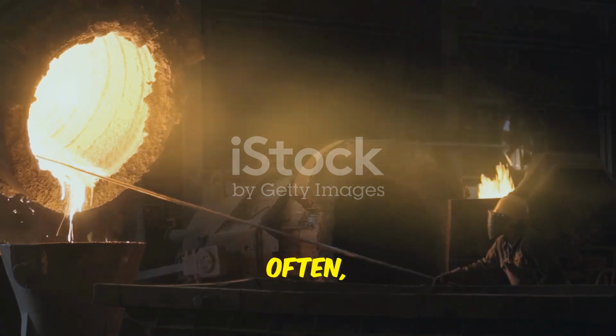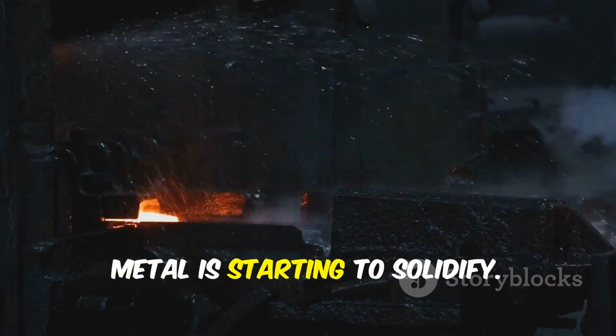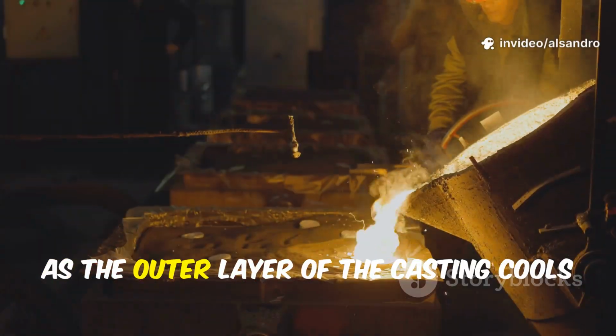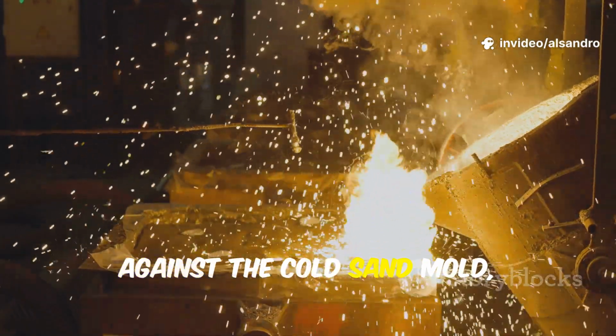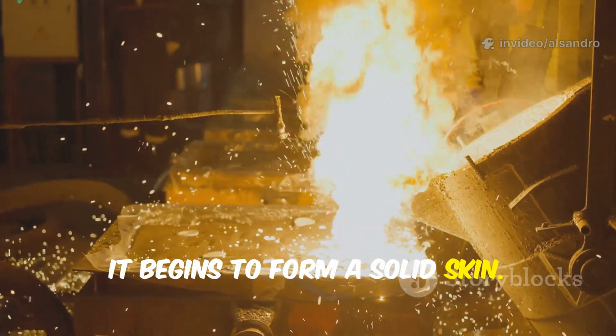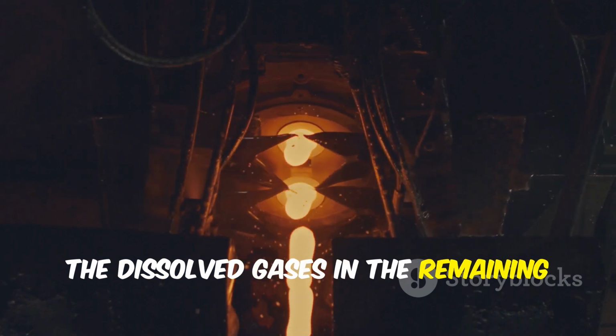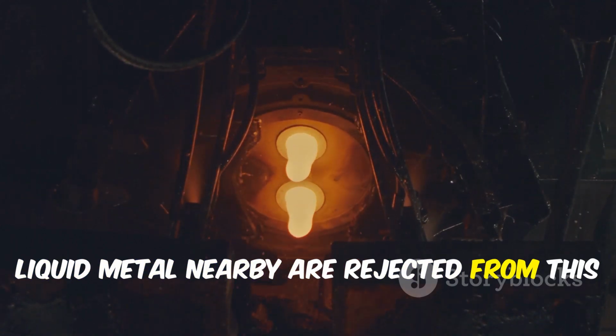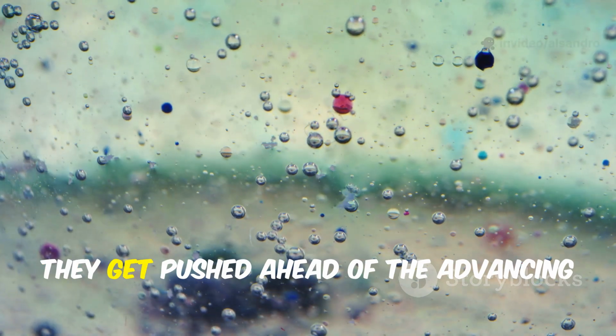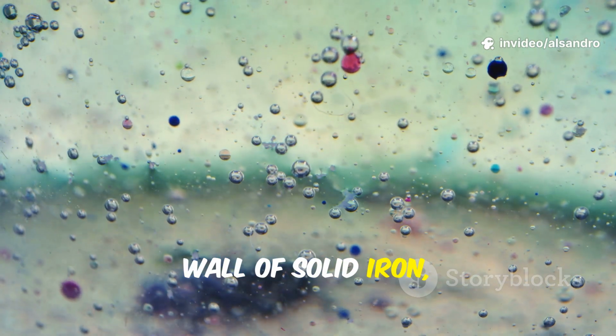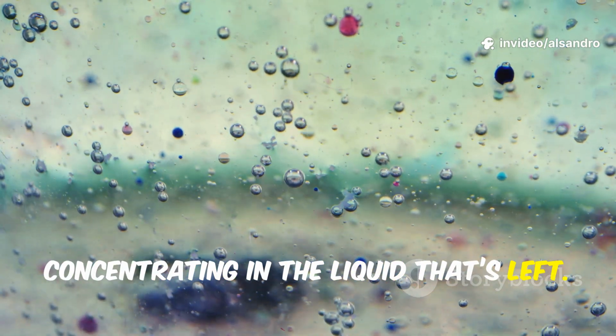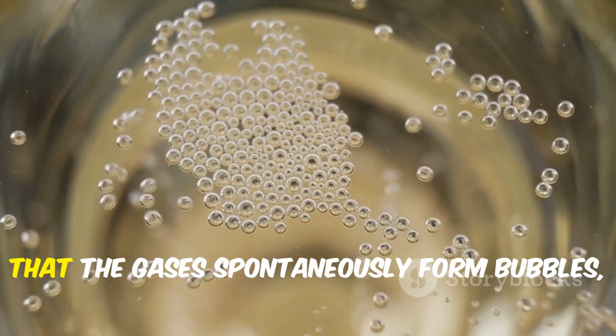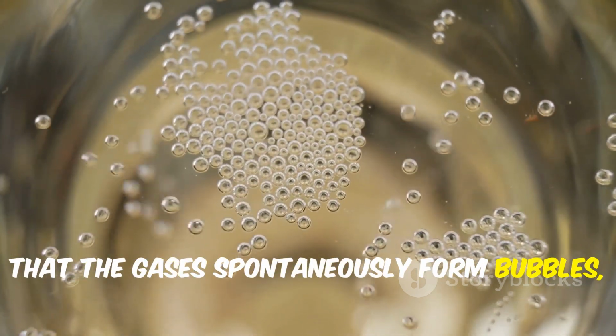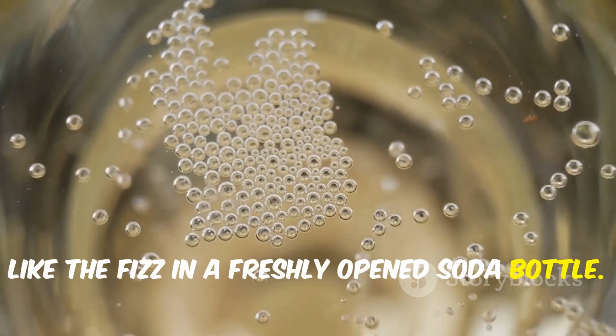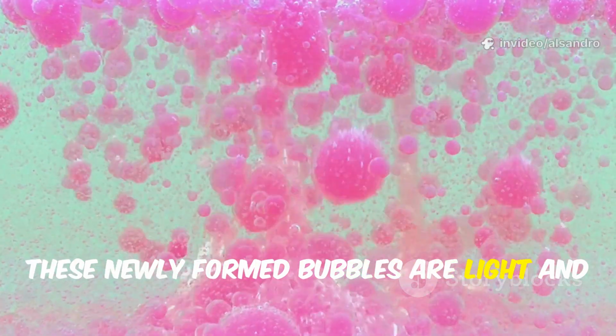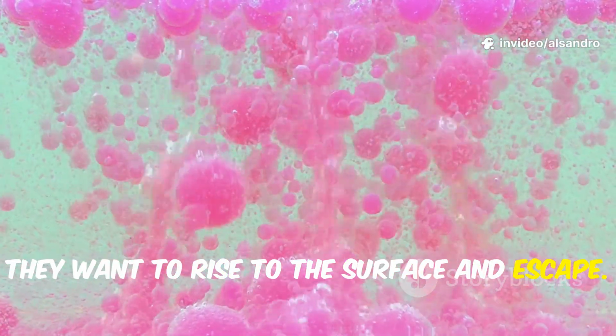But where do they form? Often they form right at the boundary where the metal is starting to solidify. As the outer layer of the casting cools against the cold sand mold, it begins to form a solid skin. The dissolved gases in the remaining liquid metal nearby are rejected from this solidifying front. They get pushed ahead of the advancing wall of solid iron, concentrating in the liquid that's left. This concentration can become so high that the gases spontaneously form bubbles, like the fizz in a freshly opened soda bottle. These newly formed bubbles are light and they want to rise to the surface and escape.